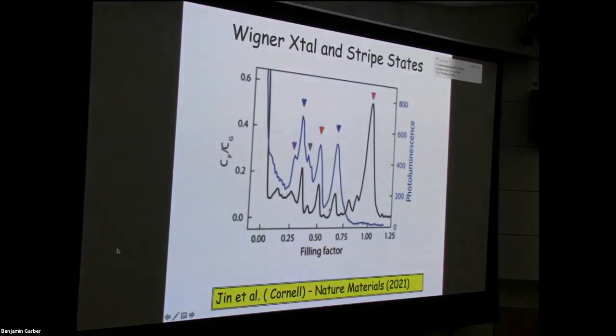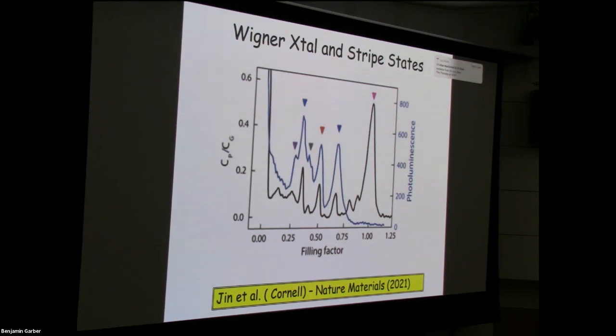These states can be thought of as more or less classical states with a small quantum perturbation, and therefore people normally describe them as Wigner crystals. But these probably would appear in many strongly correlated systems, except that there's too much disorder. So really, this is another demonstration of the possibility in these artificial systems of varying the number of electrons per atom without doping, and the chemical disorder that goes along with that.